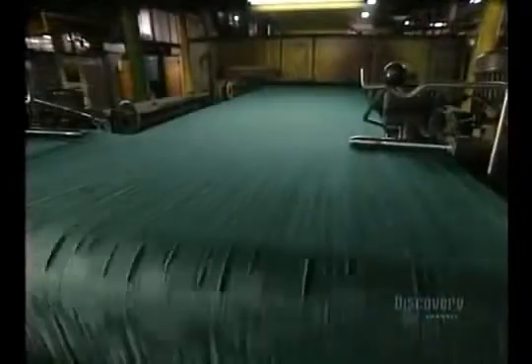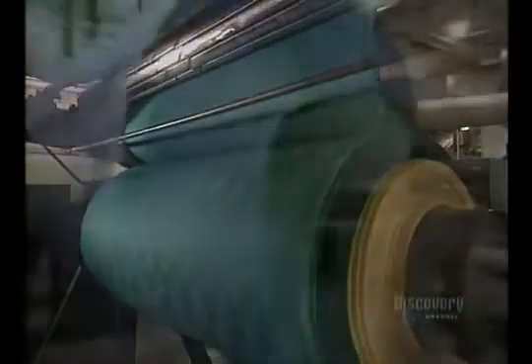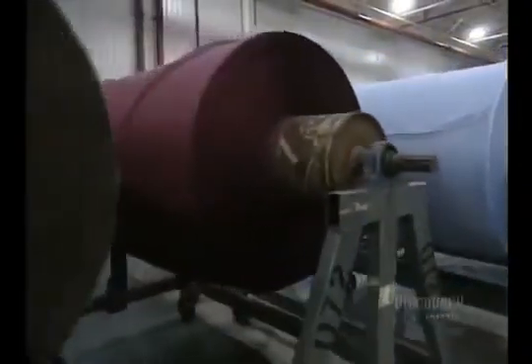We now move to thermosetting in a high-temperature oven which dries the fabric. The temperature is 200 degrees centigrade at the oven's entrance. The fabric circulates here for 45 seconds. This finished roll weighs 1,500 kilos. The bobbin that we saw at the beginning has produced